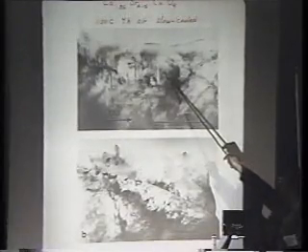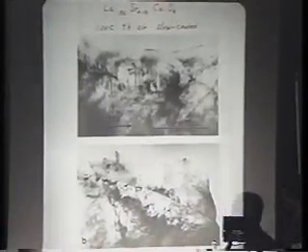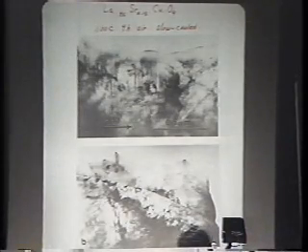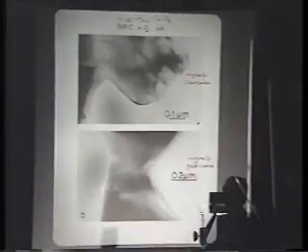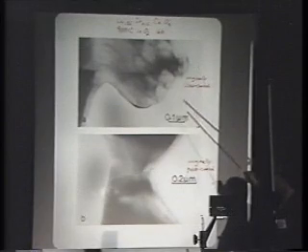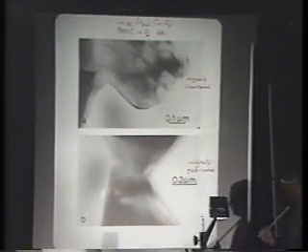For the slow cooled sample with the second phase, Steve finds that most of the second phase is present in the form of coherent precipitates, those black streaks, and this sample also has several dislocations and some stacking faults as well. Now, after the O2 anneal at 900, the material essentially becomes perfect in both cases. Single phase, essentially defect-free within the grains, and very straight, perfect grain boundaries with no second phase in the grain boundaries.